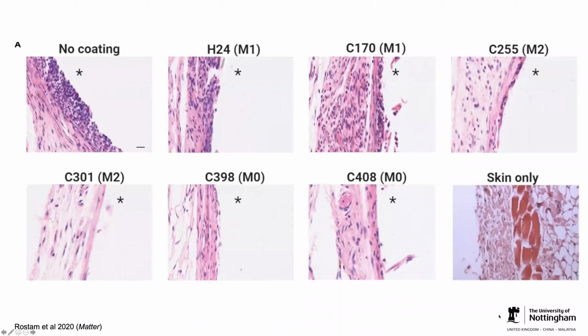So in this slide, I just show you some histology data. If you look at the bottom corner on the right, you see a histology of skin, and you see the pieces of subcutaneous fat. You have the connective tissue, and in the top left corner, this is a tissue response to an uncoated polymer. So you have a very typical inflammatory response, lots of immune cell infiltration. You have some fibroblasts showing fibrotic behavior. And even to an untrained eye, you can see that these responses are quite different amongst these polymers.